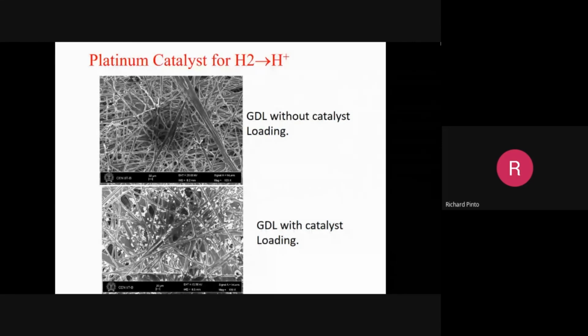You see here, distribution is not uniform. That's one of the problems. When the distribution is not uniform, the efficiency goes down. So you need a larger amount of platinum for the same effect. That is why platinum is so expensive. So naturally, the cost of all these fuel cells is quite high because of the platinum, which is an expensive metal. And also, Nafion also is quite expensive because no other membrane has been found as efficient, with as good conductivity as Nafion. Okay, this is the actual photograph we took of how the catalyst looked.